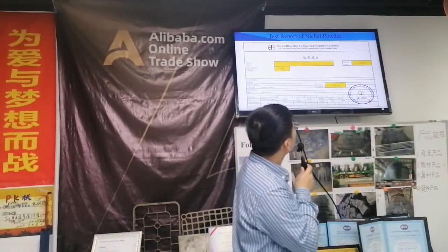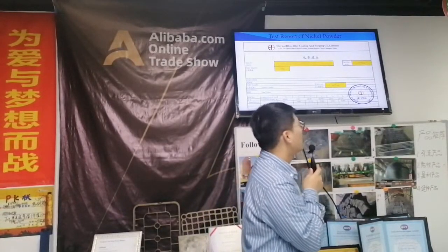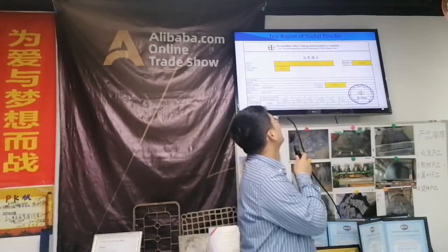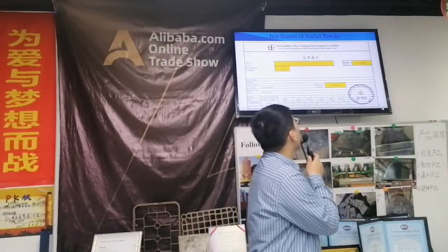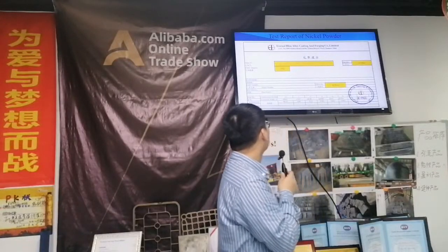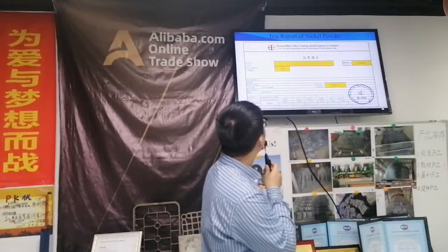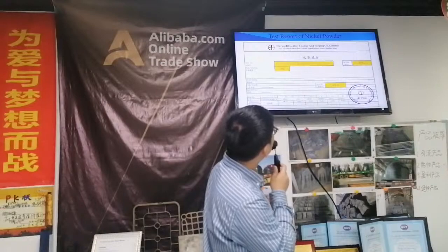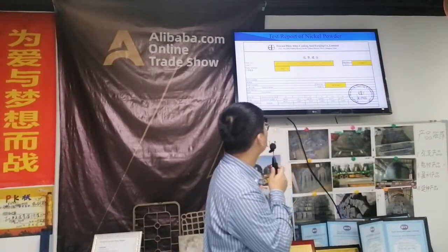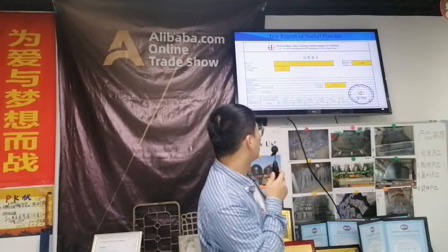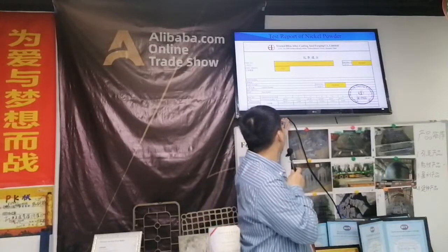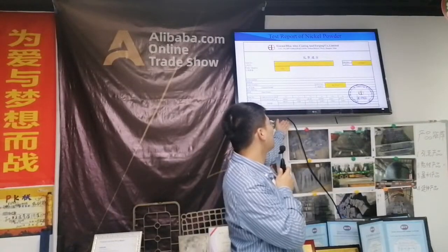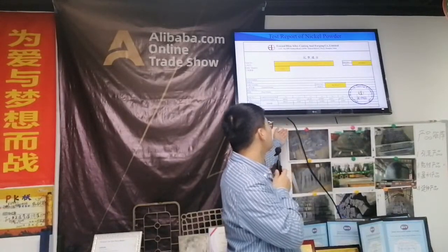The size is usually from 40 microns to 200 microns. And the composition of the nickel powder standard: the nickel takes about 99.77%.